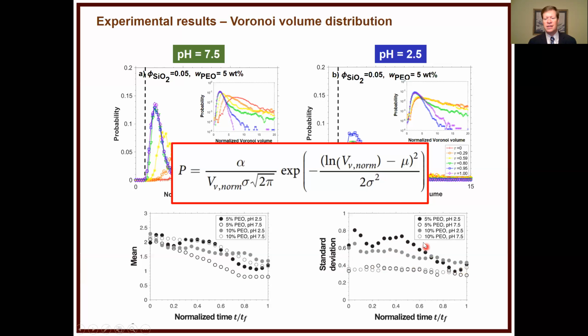And so this is a clear signature of, if you're scanning through your sample, number one, at what point is it really done drying? Well, obviously just watching scattering and motion of particles will tell you something about that. But it also could tell you a lot about whether you have a uniform effective distribution of things, where you could freeze and lock in that microstructure. You can do that very similarly in this condition, but you have more variability and yet more sample space to find microstructure that you could freeze in as well. Now doing this reproducibly is a challenge.